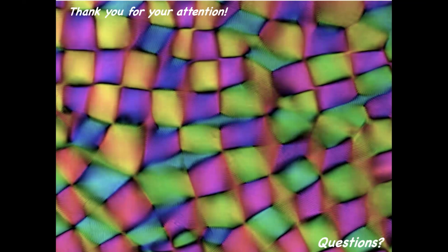Okay. Well, you talk about molecular liquid crystals. The beauty of the Onsager theory is that everything is governed by excluded volume, so it works when the aspect ratio is huge. If you start to reduce the aspect ratio, it's not only the aspect ratio; it's really the length scale. Small, you start to enter into the molecular regime, so you start to have other interactions which are not here, dispersion, van der Waals.